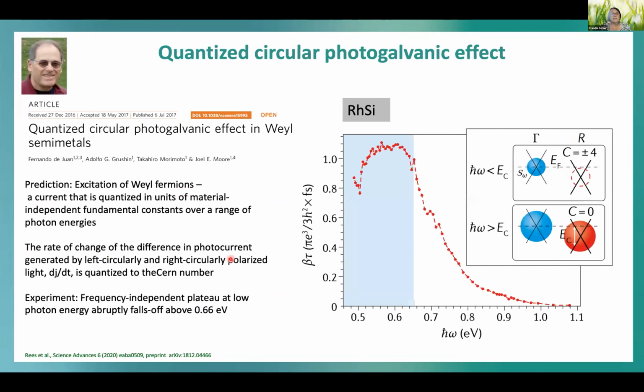So you see also, this was a prediction by Joel Moore and co-workers that you should see a very special photogalvanic effect. So if you shine circularly polarized light on this, the circular photogalvanic effect should be quantized, because the Weyl points are at different energies. And if you are able to only occupy one of the Weyl points, then you should see a quantized plateau. And there is some evidence in the measurement of Joe Orenstein done on rhodium silicide crystals, where he thinks we really see the Chern number and the plateau in this compound.